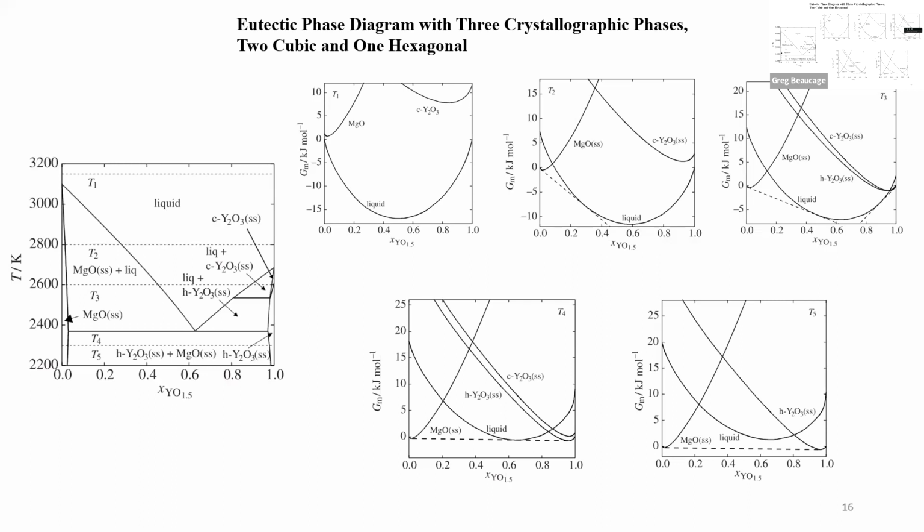So if you know the equilibrium melting point and the equilibrium heat of fusion for the components, and maybe the heat capacity of that pure component as a function of temperature, which would help but you don't need it, then you can calculate these compositions. You don't need anything else if you say it's ideal. If it's not ideal, you need a gamma, one other term for non-ideal mixing.